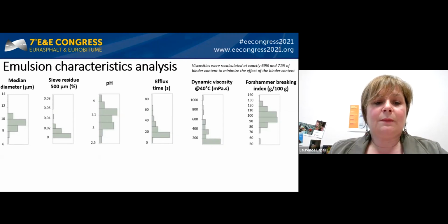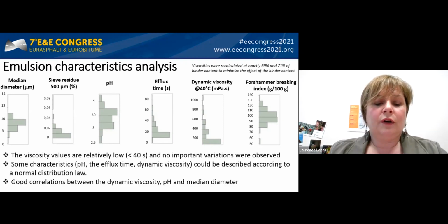This graph displays different emulsion characteristics that are the median diameter, the sieve residue, the pH, the efflux time, the dynamic viscosity, and the breaking index. First, we didn't observe high values of viscosity and high variation of this viscosity. Only few values of efflux time are over 40 seconds.